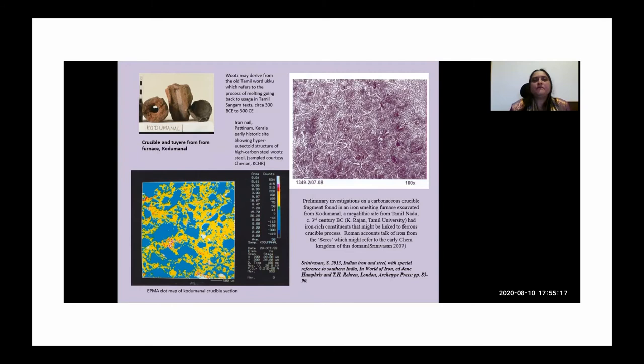And now we're also looking here at some crucibles and tuyere fragments from a furnace in Kodumanal, which is a megalithic site in Tamil Nadu, dated to about the 3rd century BCE. And you can see here that I had undertaken a cross section of this crucible, and you can see the electron probe microanalysis dot map at the bottom, which indicates again that the iron rich constituents have segregated, and it's mainly a crucible matrix related to some ferrous processing.